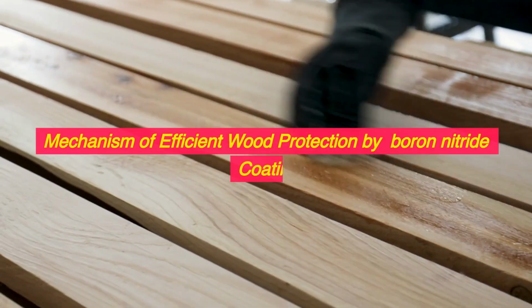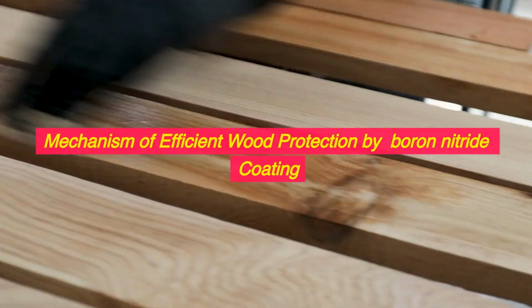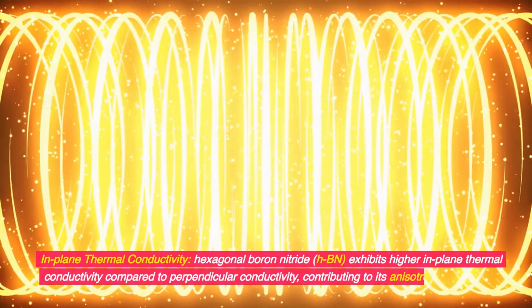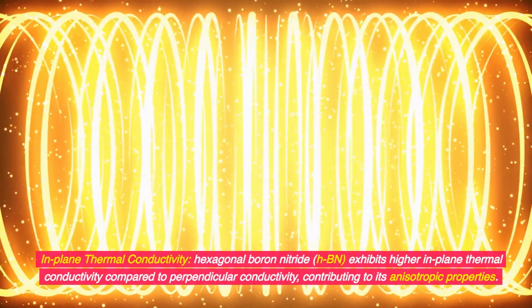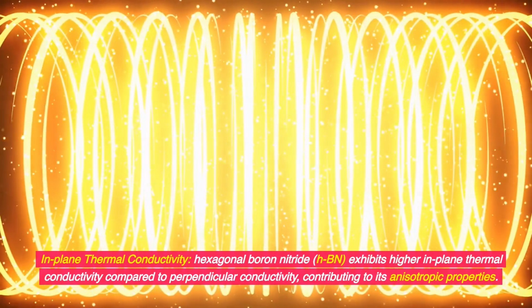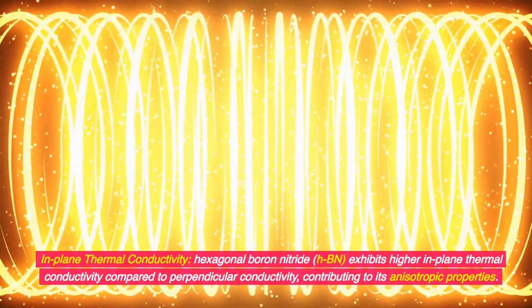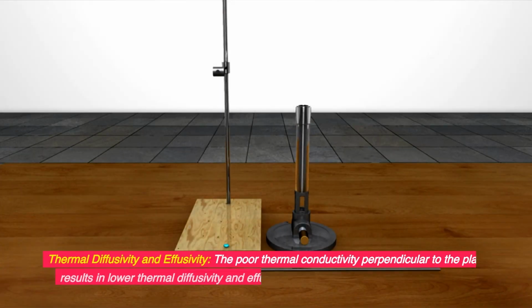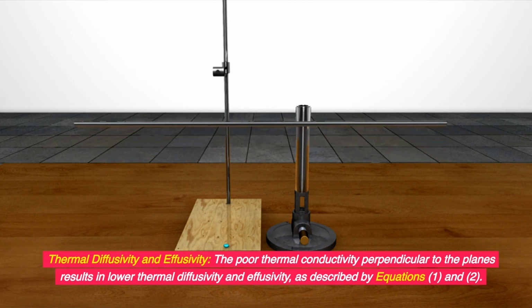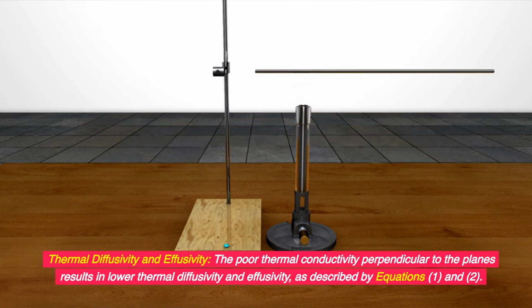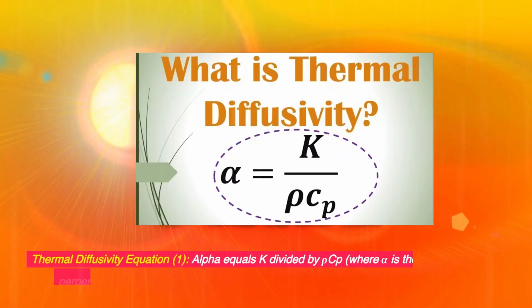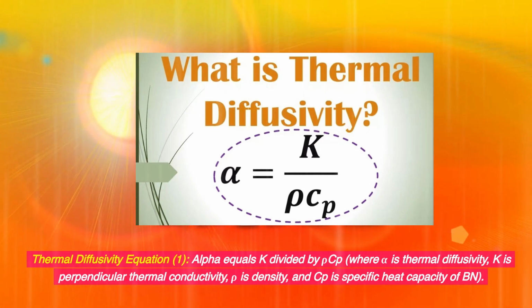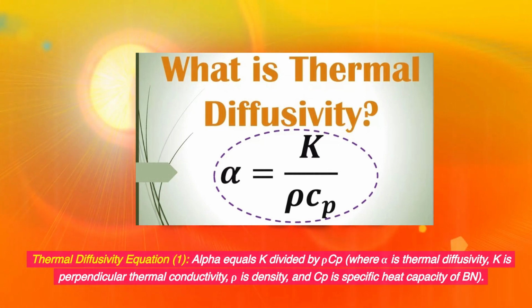Mechanism of efficient wood protection by boron nitride coating. In-plane thermal conductivity: hexagonal boron nitride (HBN) exhibits higher in-plane thermal conductivity compared to perpendicular conductivity, contributing to its anisotropic properties. Thermal diffusivity and effusivity: the poor thermal conductivity perpendicular to the planes results in lower thermal diffusivity and effusivity, as described by equations 1 and 2. Thermal diffusivity equation, 1: alpha equals k divided by rho Cp, where alpha is thermal diffusivity, k is perpendicular thermal conductivity, rho is density, and Cp is specific heat capacity of BN.